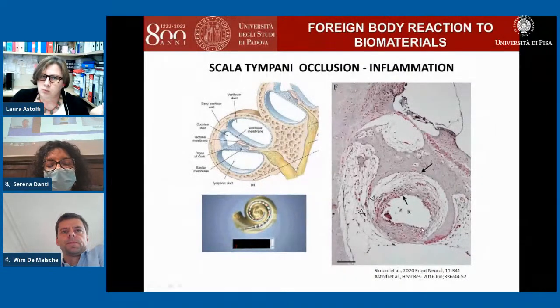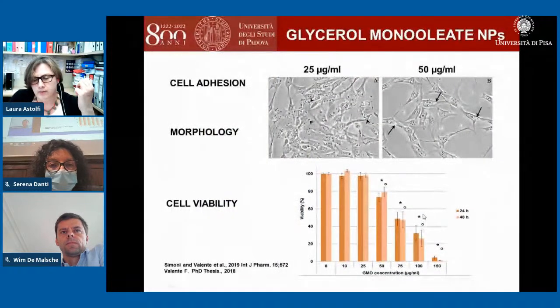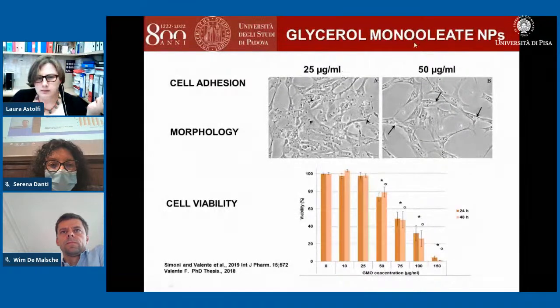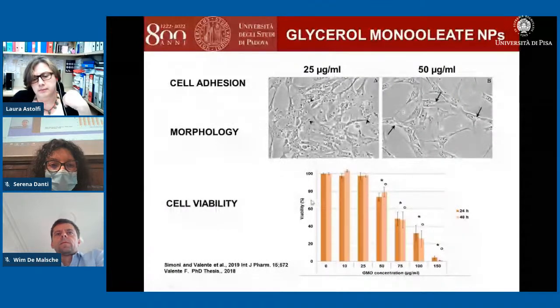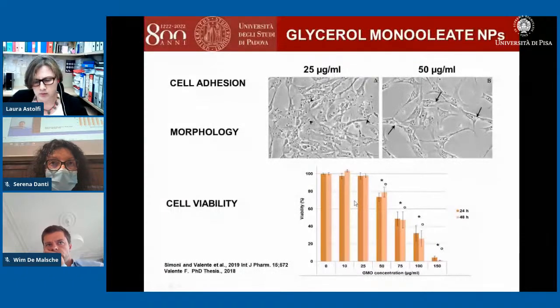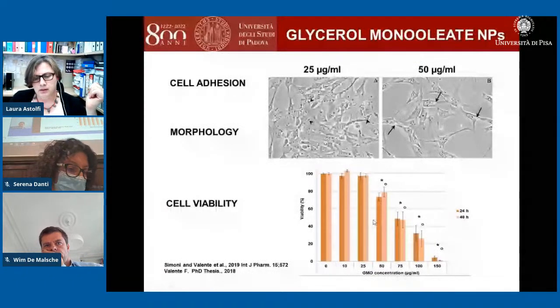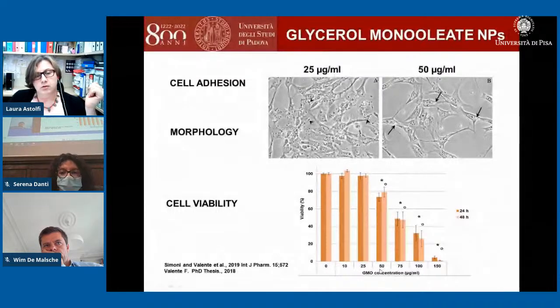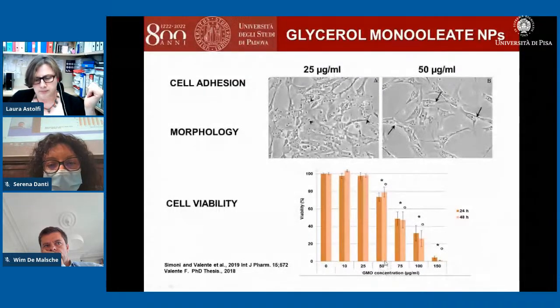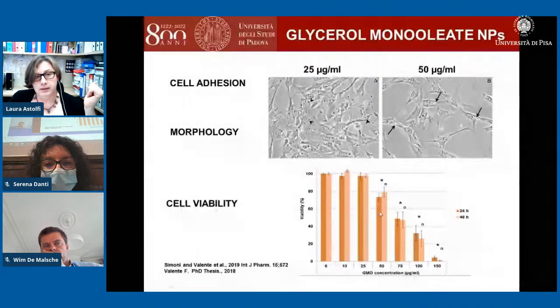To avoid this, we thought that we needed to apply a drug delivery system. As drug delivery system, we used the glycerol monooleate nanoparticles. These nanoparticles are toxic at increasing amounts, after 50 microgram per ml. The toxicity isn't dependent on the time, it is only dose dependent.